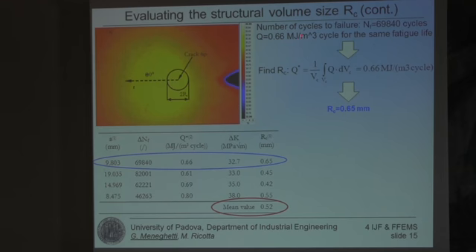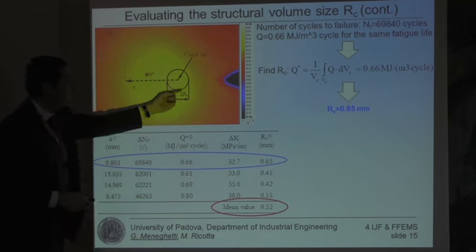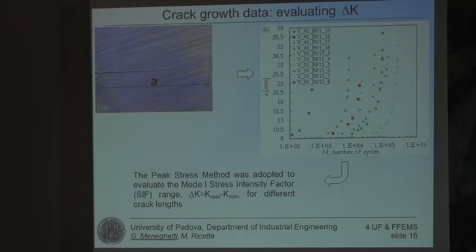Now, to evaluate the average energy, I have shown you before that we integrated the thermal flux to the boundary of the structural volume, so we had to go through these pictures. This is the crack tip. We evaluated at different angles the thermal flux, and we integrated this curve. So these are the diagrams we had to produce to perform our calculations. So now we have a procedure to evaluate the average energy, and we have an estimation of the size of the structural volume where energy must be integrated.